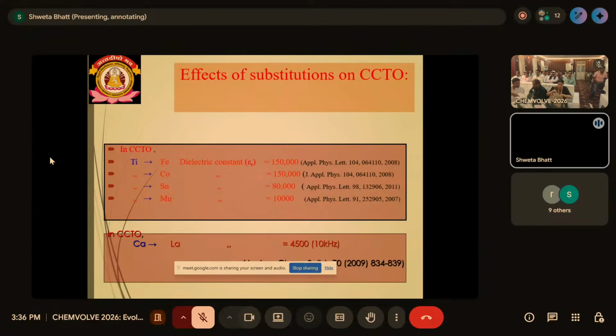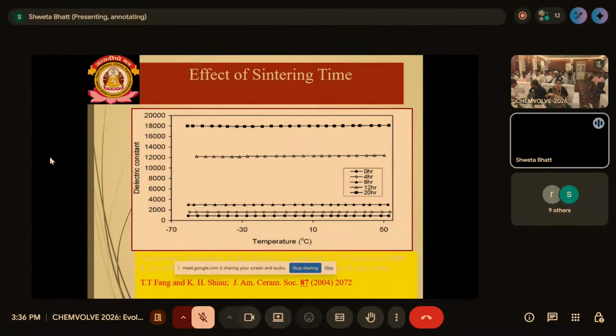So we have seen that the dielectric constant may be influenced by the substitution in that material, and we have also substituted calcium by lanthanum. In the reported literature, we can see that this substitution can affect the dielectric constant of the material. Along with this, whenever we vary the sintering time, the dielectric constant will also change. With a long sintering duration, the dielectric constant may be as high as 18,000. It means the sintering parameters also affect the dielectric property of this material.